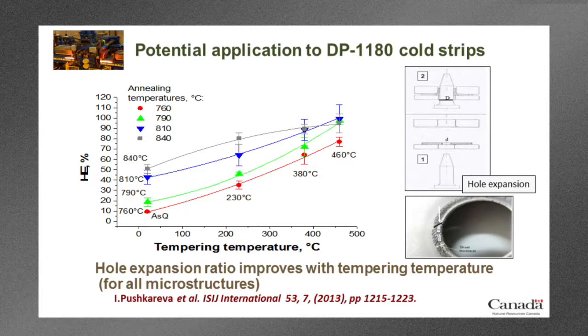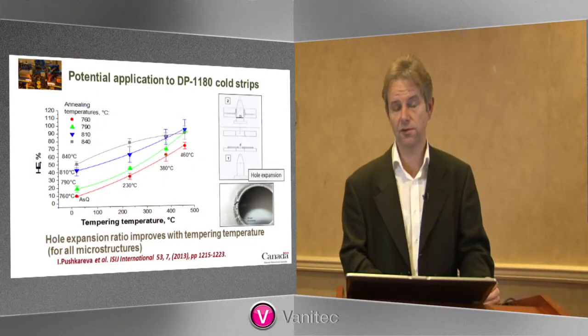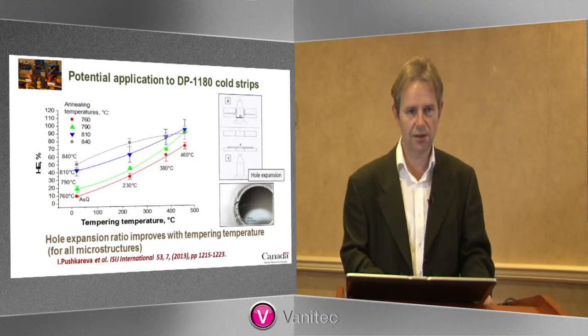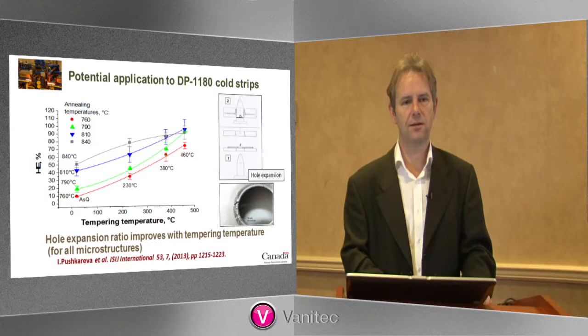So here we have the original steels in the as quenched condition at the 4 intercritical annealing temperatures that we've chosen. I remind you, here we have 38% ferrite. Here we're going up to almost less than 1% ferrite, so it's almost purely martensitic steel. And what is interesting, and what you would not expect intuitively, is that the steel with no ferrite, so no soft phase, a very, very hard steel which has very low ductility, has actually got the better hole expansion coefficient. And that's because you don't have this dual phase structure, you don't have these interfaces where you have this strain partitioning. So a single phase martensite is actually better than a softer dual phase martensite ferrite steel in this particular damage resistance or this damage measurement experiment that we do.